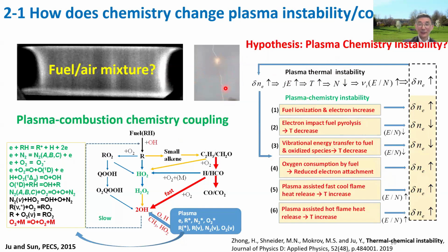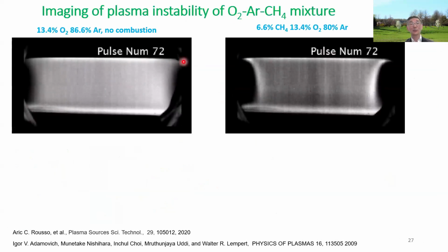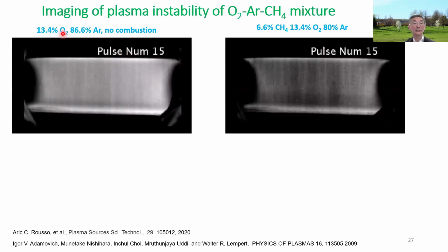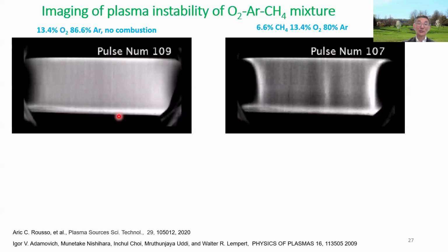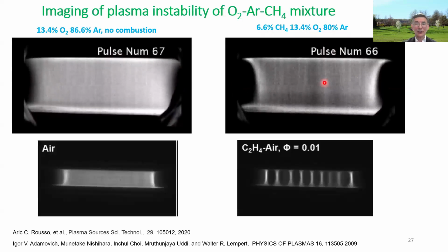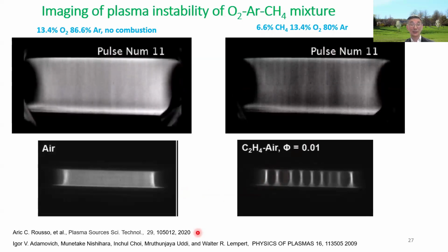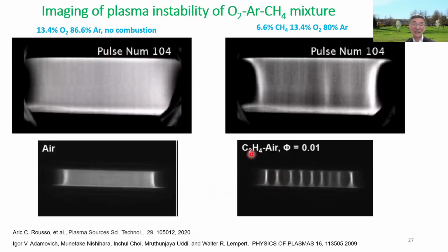Luckily the proposal was funded, and I had the opportunity to work, and I asked my students to do experiments. Oxygen and argon mixtures with a nanosecond discharge give a very uniform discharge. If we add 6.6% of methane, replacing argon, you can see the plasma start to contract in a few milliseconds. Then I looked at the literature and found that Igor Adamovich also observed this early in 2020, showing that when you have ethylene in air, the plasma becomes unstable, but he never explained it. So I thought there was an opportunity to use combustion to explain this.